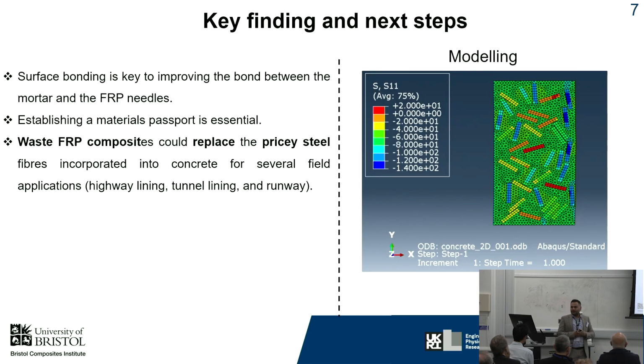I'm constructing a model with randomly distributed needles inside a cylinder to study the elastic modulus, compressive strength, and split tensile strength. The key finding is that surface bonding is the key to improving the mechanical property of the cement. Establishing a materials passport is really important, to know where we got those materials and what kind of materials we have. In my PhD, I had to go through a series of experiments such as burnout tests, moisture uptake, and all sorts of materials tests.